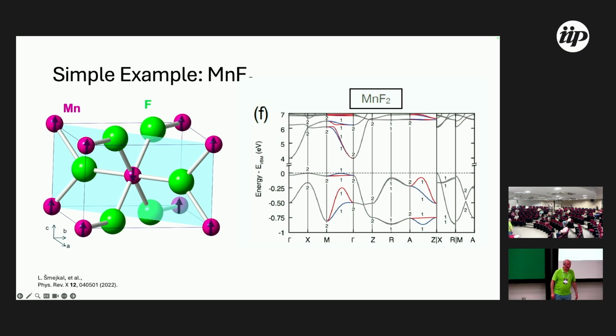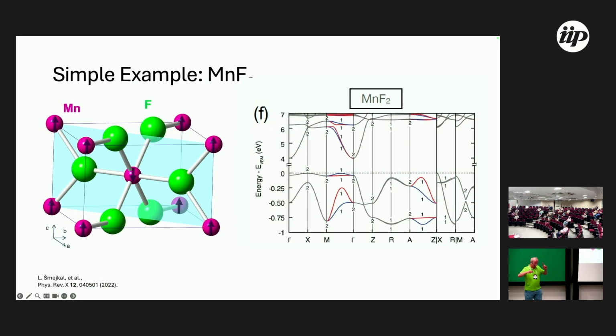To see if we understand this, there is only one polarization direction in position space, like in an antiferromagnet. So up, down with respect to some direction in the material. It's not canted through the material, the quantization axis. That is right. In this case, the magnetization is completely compensated, and there's a strong C-axis anisotropy, especially in the cousin of this, iron fluoride, where this anisotropy is really large. But yeah, that's how collinear altermagnets work.